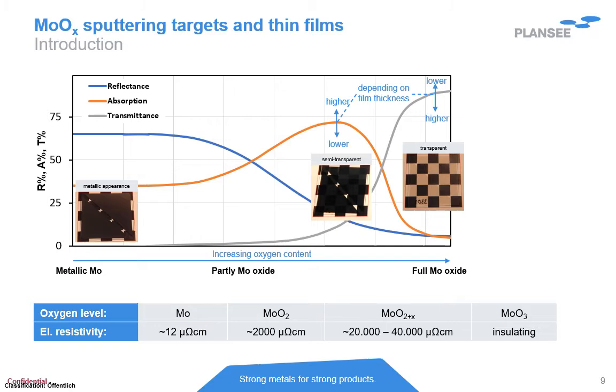If you're increasing the oxygen content, you will get more and more properties from the oxide range, which are high electrical resistivity up to completely insulating for MoO3, and also the optical properties are changing a lot. For example, if you have a composition between MoO2 and MoO3, you can achieve that the oxide thin films are highly absorbing, which is making them interesting for anti-reflective coatings. If you're going to the MoO3 stoichiometry, those thin films are highly transparent, for which other applications are interesting.